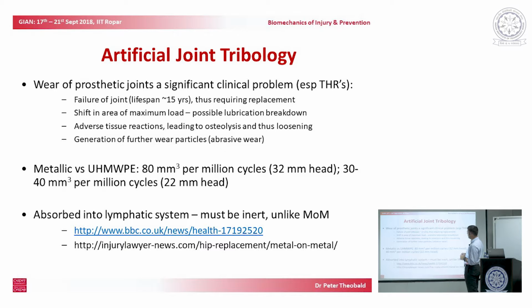And so this touches on the engineering aspects of tribology, again, of artificial joints. It's predicted that per million cycles of a metallic versus polyethylene component, you get about 80 millimeters cubed of wear debris. That's from a femoral head, so a metallic head that's 32 millimeters in diameter. However, if you reduce the head size, it's possible that you can reduce the wear. But this is very much dependent on the precision of fit and the use of the implant by the patient. And so these are only indicative numbers.